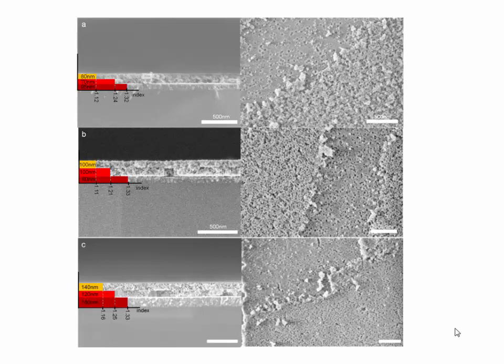In that way, we are able to achieve distinguishable multi-layers, and if you scratch off the top layer, you can see the second layer underneath that. For each of the 3-layer structures, we see that the top layer has a higher porosity than the bottom layer, for all 3 multi-layers. So that proves that we can actually have a multi-layer stack.